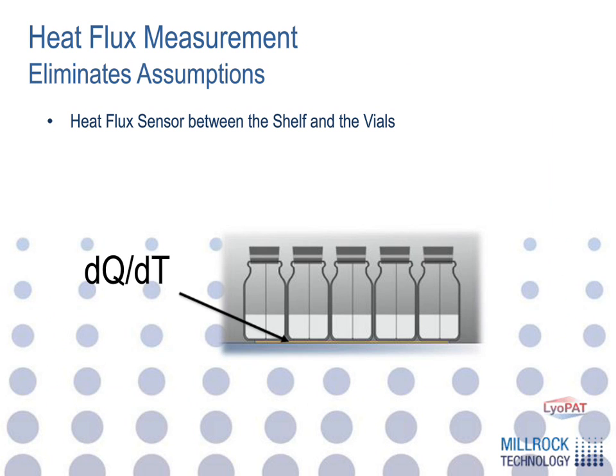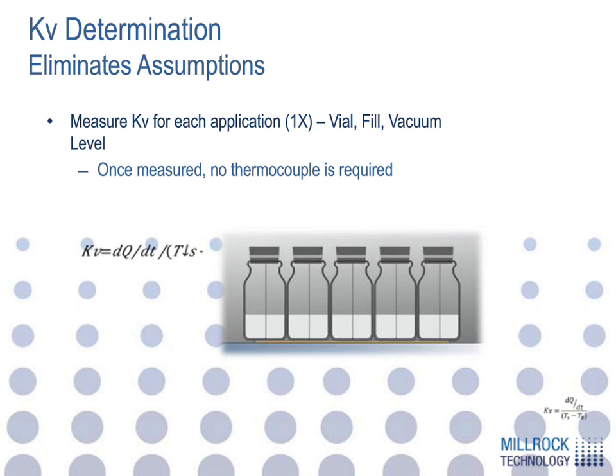The heat flow measurement that we do uses a heat flux sensor that's placed between the shelf and the vials so that we can actually measure the amount of heat coming from the shelf into the vials, or vice versa, depending on whether you're heating or cooling the process. Now, what we can do with this is if we add a thermocouple to the process in the vial, and we can add a thermocouple to the shelf, we can actually calculate the thermal conductivity of the vial, or actually should say measure it, because we have the heat flow. If you look down in the lower right-hand side, you can actually see the equation. It's a very small equation there where Kv equals the heat flux over the temperature of the shelf minus the temperature of the product, and that's times the area. So we can actually determine what the Kv of the process is.